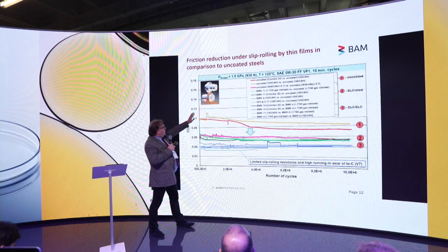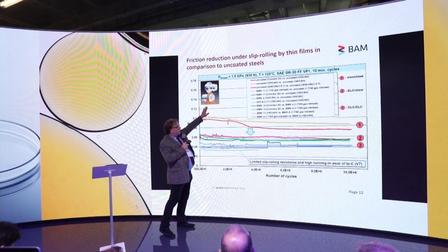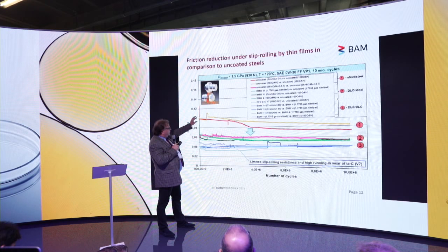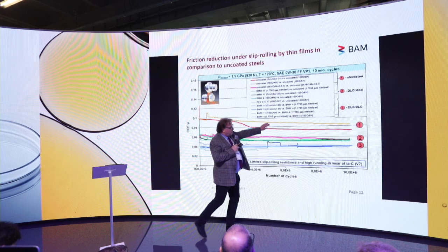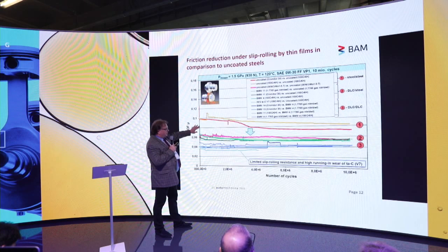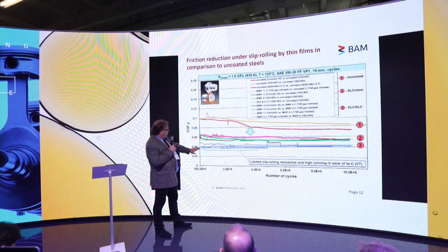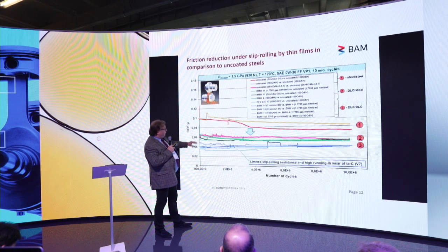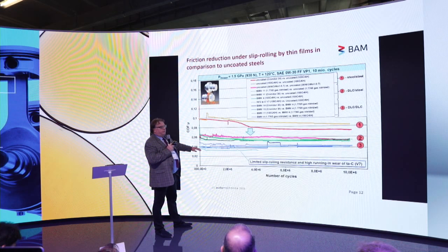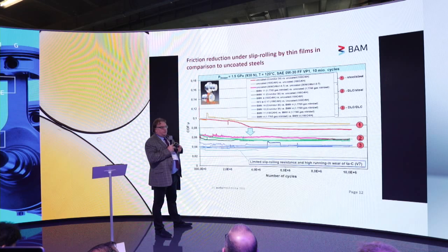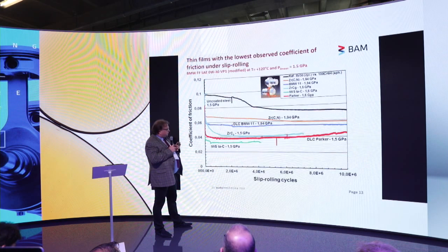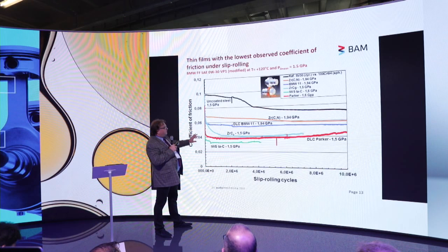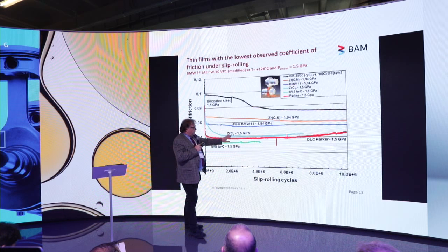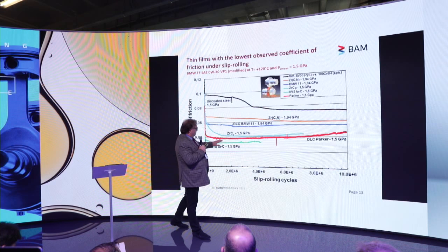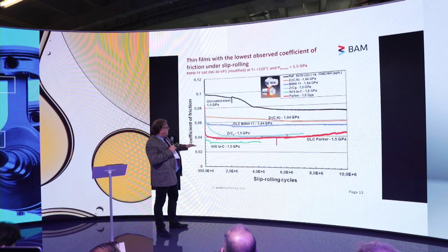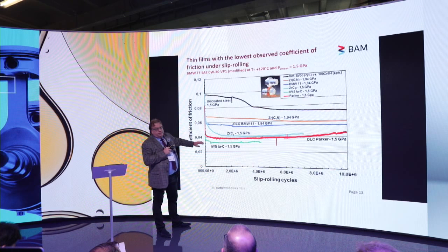Second option, you have here the rolling contact. Now you make thin film coatings. This is uncoated. You have 0.08, let's say. Now you coat one surface, and now you coat both surfaces. So you can go down to 0.04, let's say. You can reduce by 50% just by changing the coating or the alloy. Here you see the best performing coatings. Can be zirconium carbide, DLC, or a diamond coating. So you can reduce friction by 50%.